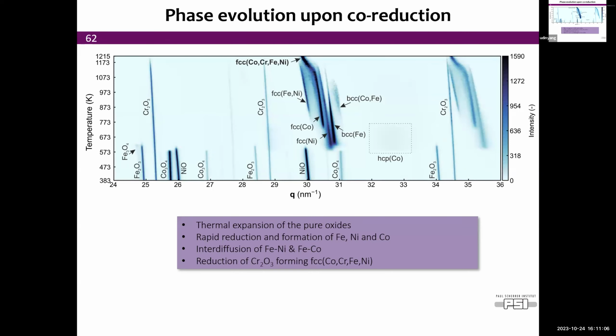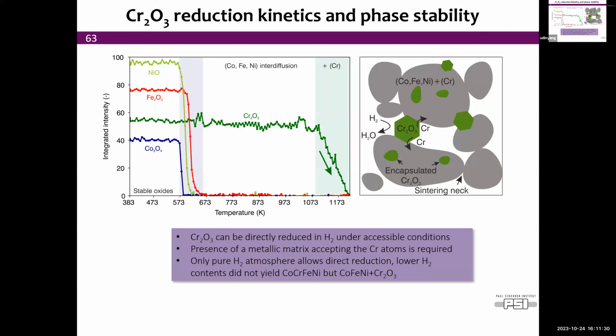But then it disappears at the highest temperature here, and you get a drift of that diffraction peak, indicating that we're alloying with chromium. And in fact, the cross-section that I showed you, if you do EDS, you see that it is really fully homogeneous. So at the very last moment, the chromium oxide disappears, and we end up with a single FCC cobalt, chromium, iron, nickel, entropy, or multi-principal alloy.